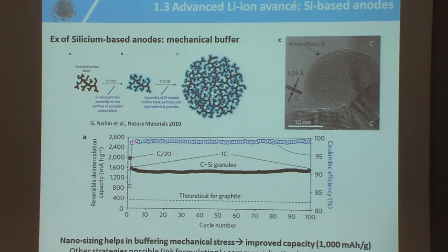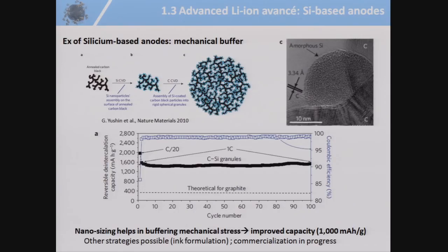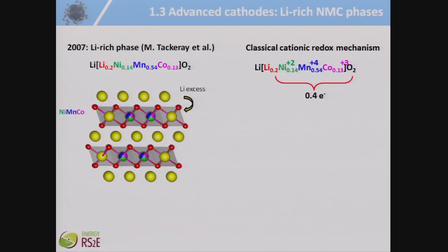Have a look. Cyclability is very good. Capacity, 1600 milliampere hour per gram. You limit the number of lithium intercalated, alloyed lithium, by 2.5, no more. And then you have something very stable. So this is an example of how to make a silicon-based anode. You have plenty of other strategies like ink formulation, and the commercialization, I would say, is in progress. But this is a very, very hot topic.